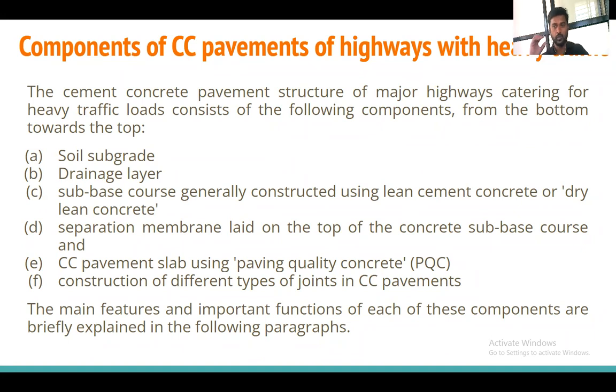Okay, DLC and PQC. These are two important words. DLC, dry lean concrete. Over that, the separation layer of the 125 micron polythene sheet is placed. Then on that, PQC is done. That is paving quality concrete. Okay, so these are the two important layers that we need to study in cement concrete pavements.